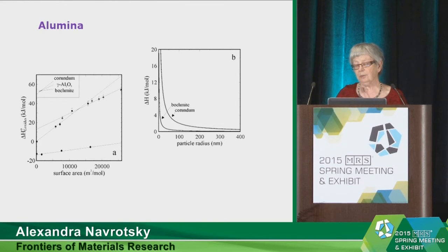and you say, well, when is the material really nano? If it has a small surface energy, like gamma alumina, you really need more surface area before you notice that the properties are different. So the term nano itself is relative. It's for what property, it's for what surface energy, it's for what function. It's for X-ray line broadening on the one hand, it's for crossovers in stability on another. There's no absolute, you say this is nano, that is not nano. You have a particle size distribution. So to me, something becomes nano when something you're interested in becomes significantly different.